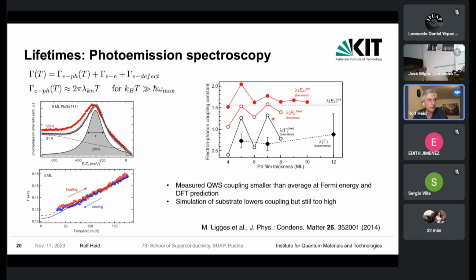And we find a somewhat slightly different behavior. So you see that the coupling, as in experiment, is significantly reduced compared to the coupling strengths we have found for the superconducting properties. So these specific individual electronic states have a smaller coupling. However, we still have some mismatch compared to the experiment.